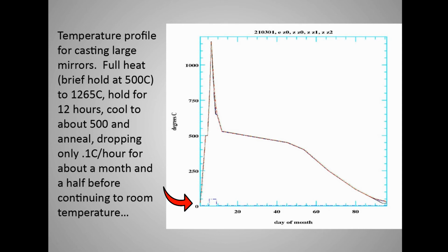They have a brief hold at 500 to make sure, if they go beyond that point, the glass starts melting together, which is bad if you need to change something. So they bring it up there, and they have like an 8-hour hold. And if all goes well, then they continue to go up. I think they can go up at about 25 degrees per hour centigrade, the max they can go. 1265 is the maximum, and they hold that for 12 hours.